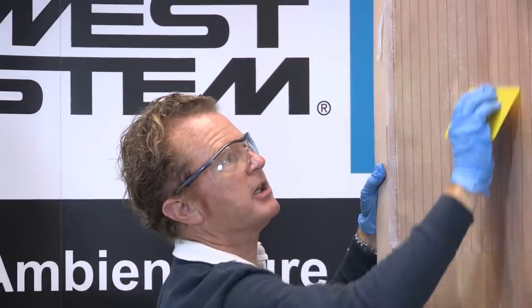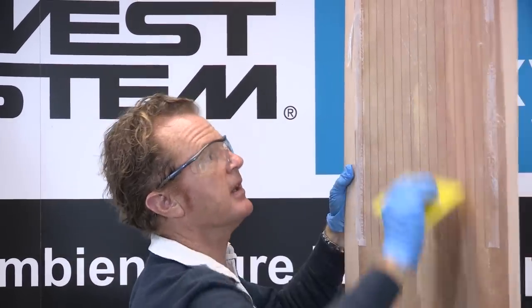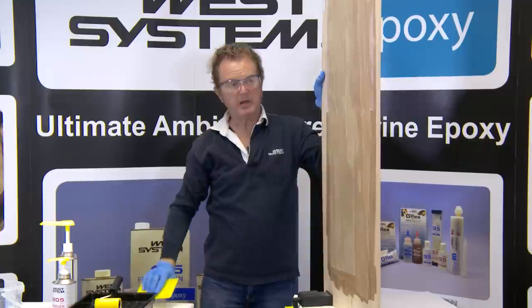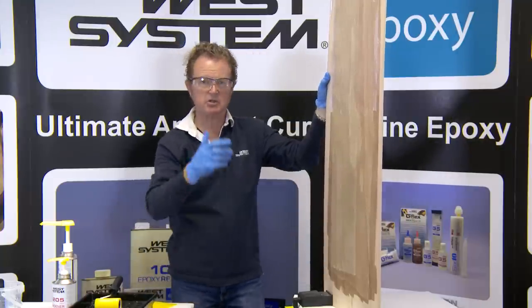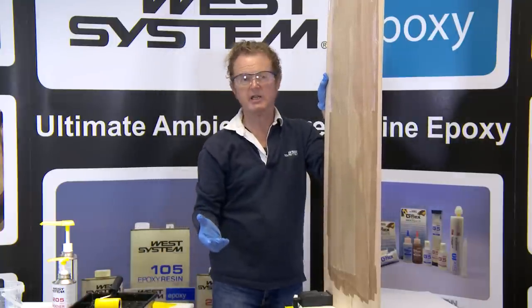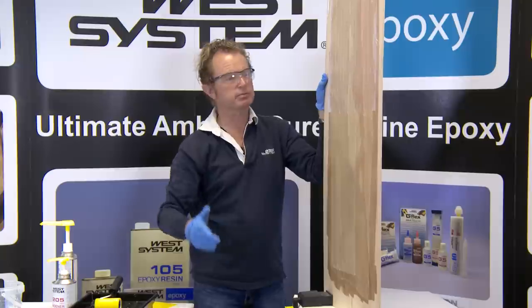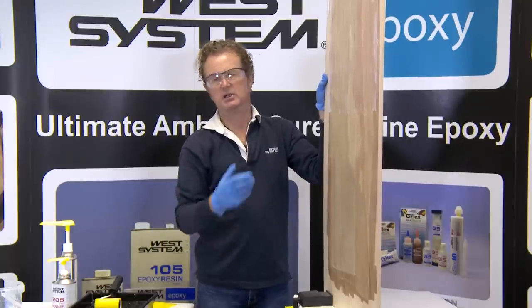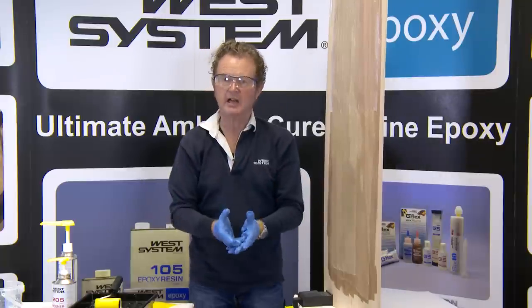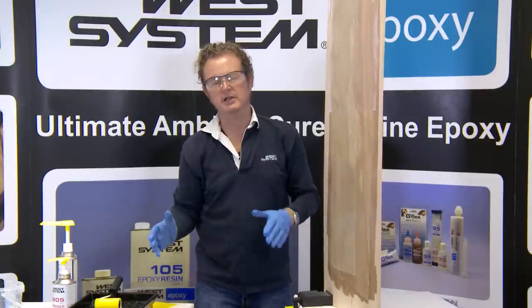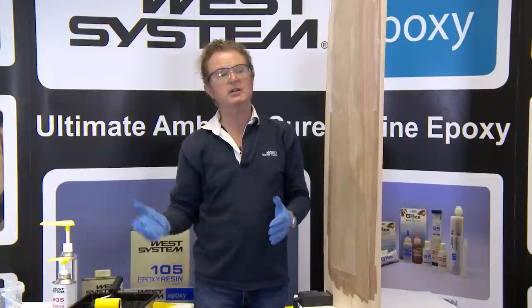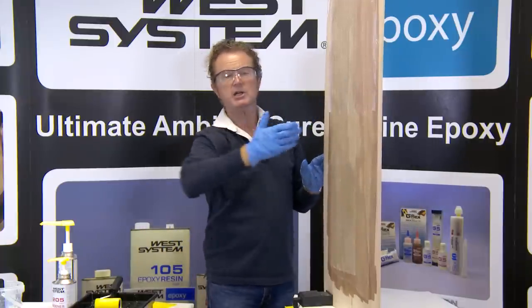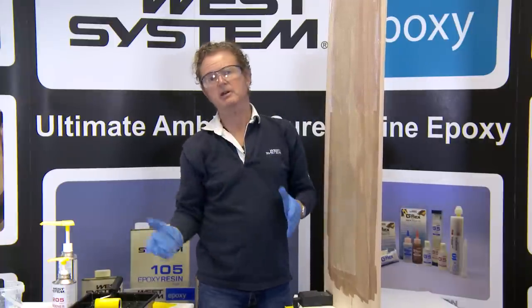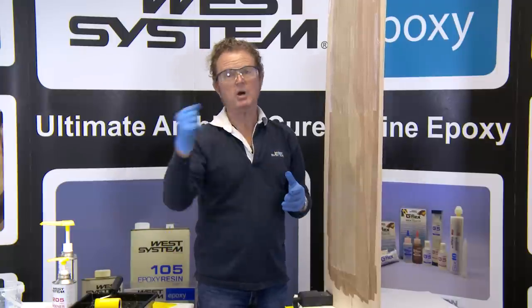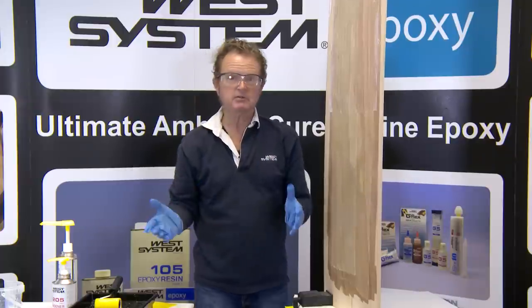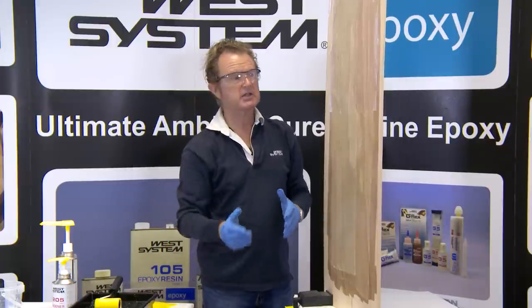Now, this will work fantastically on a boat that's having a new deck put on it. If you are fitting a new plywood deck, it would be really, really good practice to sheathe the deck with a glass fabric. Now, of course, once you've done that, you're likely to want to walk all over it, maybe for 6 months, maybe for another year. And it's quite feasible to leave the peel ply on for that period of time and then rip it away once you're ready to maybe fit the teak deck or you're ready to paint the decks.